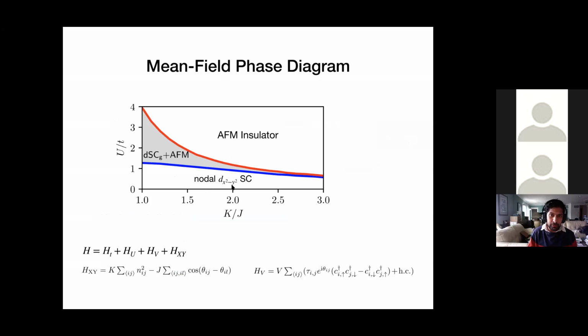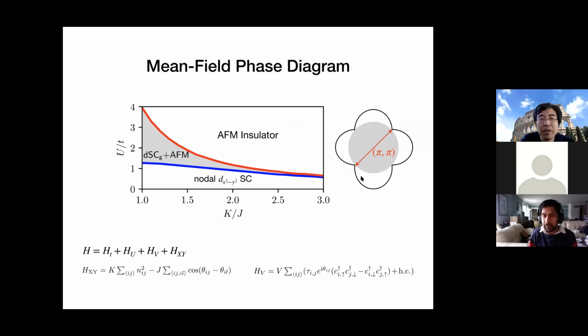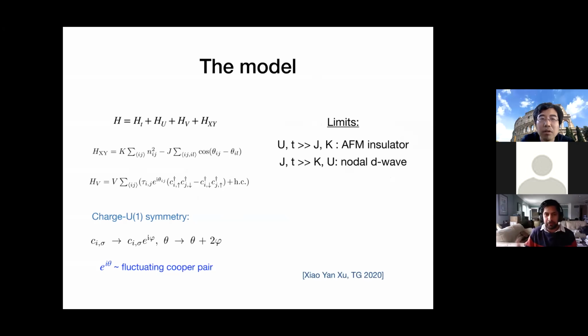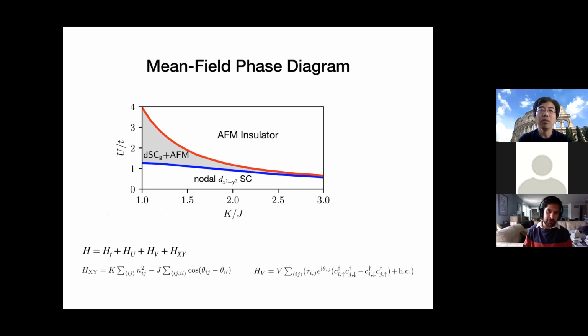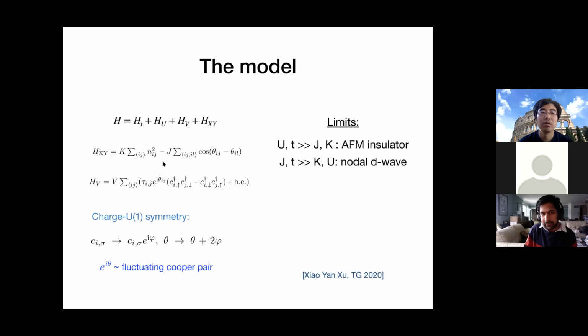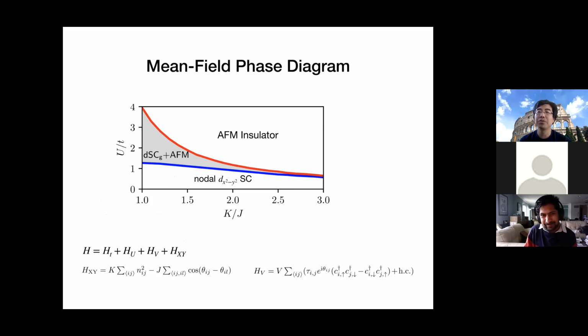So this is the mean field theory you can do. One thing you quickly see is that there is an intermediate phase. One way to think about that is that once you first go to the D wave phase, there are more parameters, like you have 4 parameters. So we explored the space, and as far as we can tell, there are no other phases. We took some slice which gave the representative phase diagram. We set J to 1 and T to 1 and V to 0.5. It doesn't matter which of T and J is larger. It will move around the phase diagram, but the topology will remain the same.